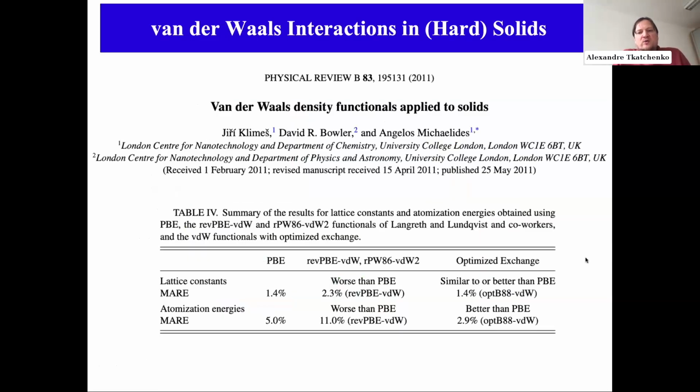Of course, we are not the only people that worked on the importance of van der Waals interactions in solids. This is quite a prominent paper from Jiri Klimeš and Angelos Michaelides, who demonstrated that by empirically optimizing semi-local exchange in density functional approximations and coupling this to the non-local van der Waals functional of Langreth and Lundqvist, you can actually get better results than PBE for the cohesive energies of solids and get lattice constants of solids with essentially the same accuracy as PBE.